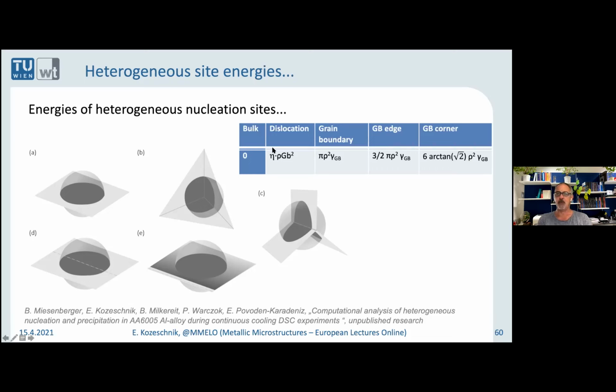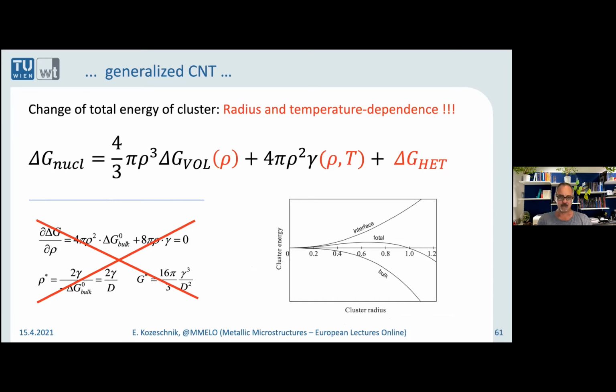So we now put this energy as a favorable term into our nucleation energy. And here's a proposal for dislocation energies, and here's the proposal for the grain boundary corner. And you can always see this is the energy of the grain boundary, which is a very important ingredient here. So with this theory, we went into the nucleation rate again. We used the extended classical nucleation theory. That means we consider the volume free energy change as a function of radius. It's not in the present calculation, but the interface energy is a function of the radius of the particle. It is a function of temperature because we have this diffuse interface effect. And we take into account the heterogeneous site energy that is related to the nucleation site.